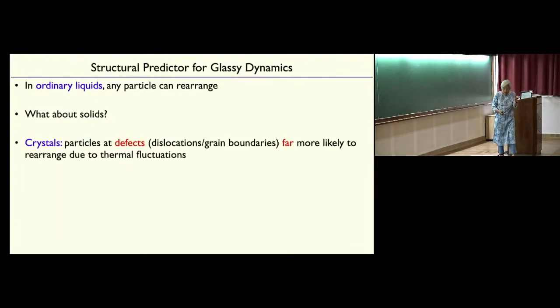So this is where we come to this idea of a structural predictor for glassy dynamics. Because in an ordinary liquid, any particle can rearrange at any time. They're roughly equal. But in a solid, that's not true at all. In crystals, we know that it's particles at defects, primarily dislocations and grain boundaries, that are far more likely to rearrange due to thermal fluctuations, whereas particles deep inside crystalline regions are very unlikely to rearrange.